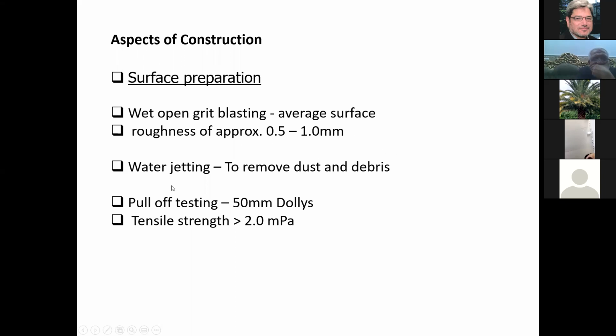And we also do what's known as pull-off testing. The concrete has to have sufficient tensile strength in order for this material with its epoxy to act compositely with the concrete. So the minimum tensile strength that we required for this bridge was 2 MPa. And this is something that we do by doing pull-off testing, and I will show some pictures of that test.